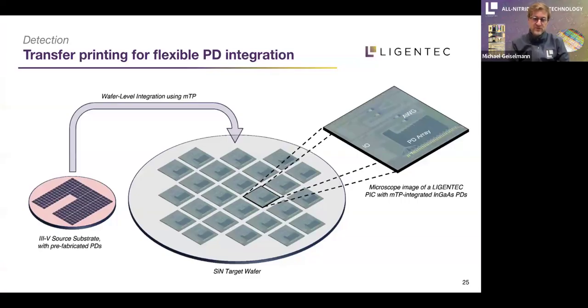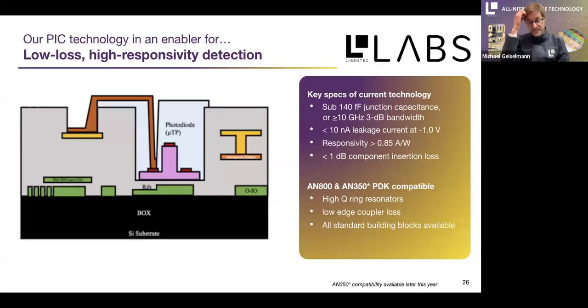And we chose to use microtransfer printing here for integrating PDs, where we source III-V PDs from a source substrate, where they have prefabricated photodetectors on that substrate. And then we go to our silicon nitride target wafer and use this technique called microtransfer printing, where you take like a stamp, you take that photodetector, pick it up, and then pick and place it to your target wafer, where you then can integrate these PDs on silicon nitride on a wafer level scale.